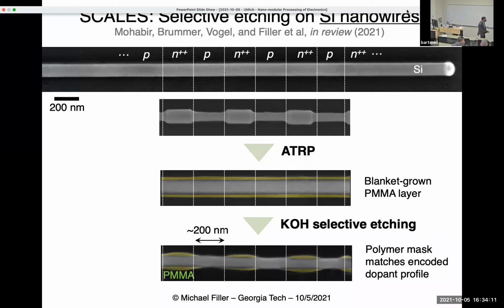And I'll point out that the spacing between these masks, this channel region, is already deep submicron, 200 nanometers. And that's without trying too hard. Nanowire growth has been shown to get down to tens of nanometers really without trouble in terms of dopant profile control. So we have room to be better. But this is basically quarter micron, late 1990s silicon technology, but just done with an entirely different, mostly bottom-up process.